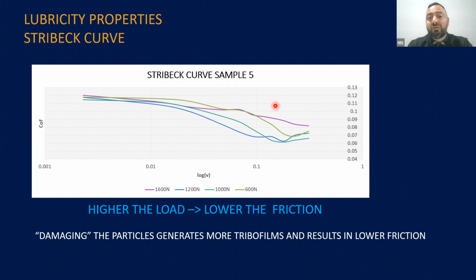Of course, to a certain extent. Here, at 1600 Newtons friction went up. That means that maybe you need more particles in an application where there are much higher loads, and that's going to be fine. But you need to see what loading you need based on the system. Maybe you need 0.5%, maybe you need 1%, maybe you need 2% of particles. But the actual trend is the more you damage the particles, the more effect you're going to get out of it.